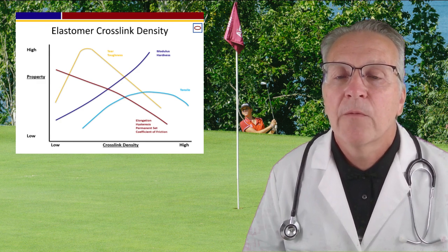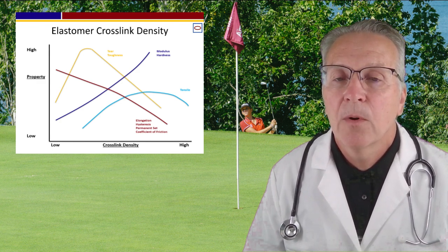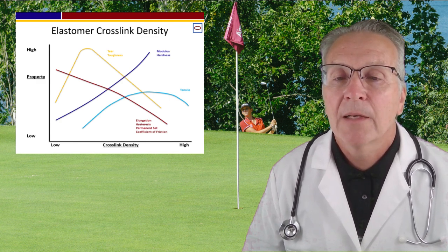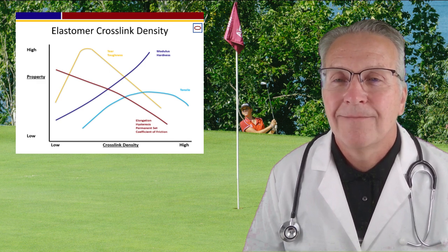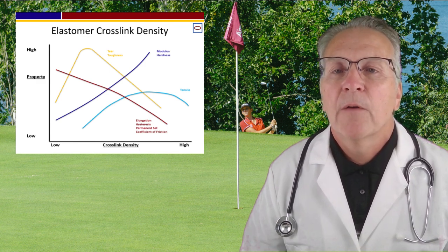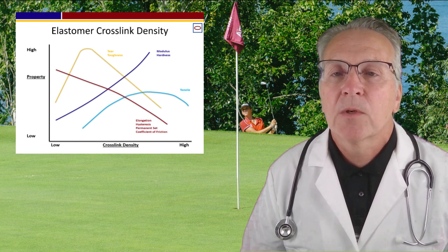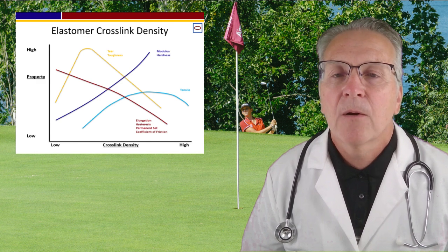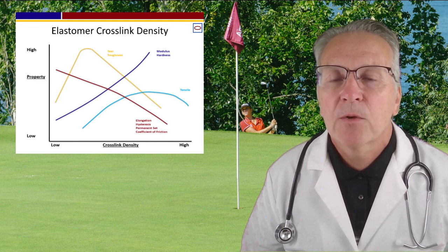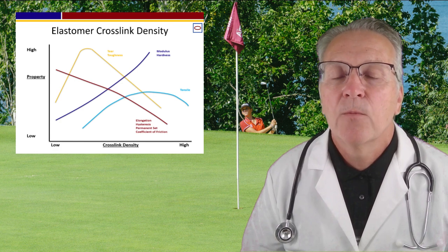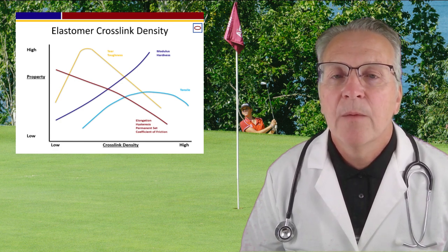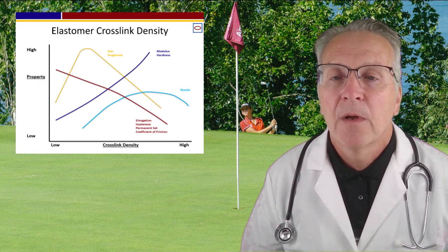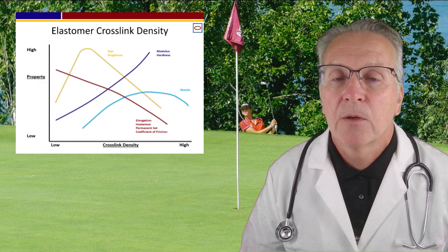And we saw lower tearing values for a tighter polyisoprene network at room temperature compared to a looser polyisoprene network in a past That's Working Knowledge video. If you have ever removed tightly cross-linked elastomer slabs from a compression mold, you will know they are often so brittle that they tear on demolding. We see the same trend for toughness and tensile strengths, in which higher crosslink density levels limit elongation, which limits toughness, or the area under the stress strain curve, and also limits tensile strength, shown in light blue.